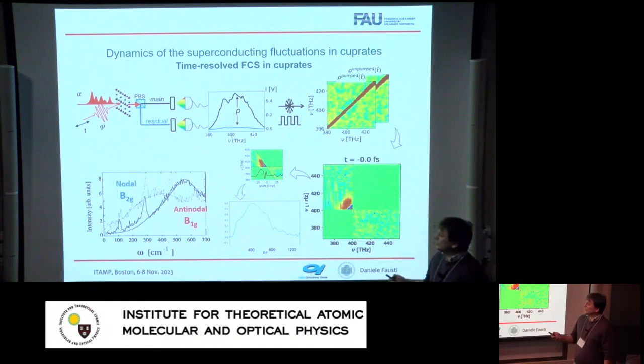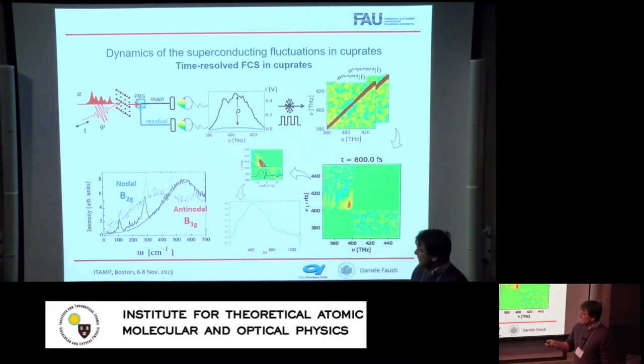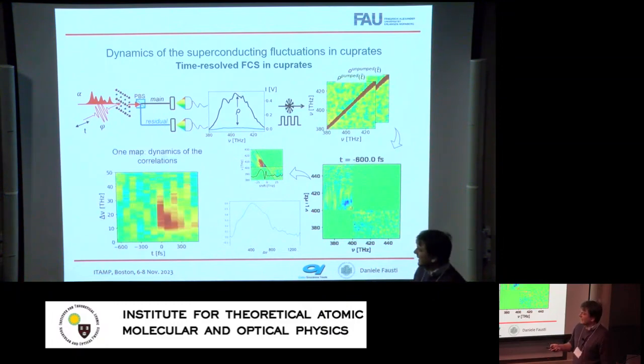What could turn out to be a very interesting observation is the following. Now I can measure how this Raman scattering evolves in time. So I can measure information which tells me, after I perturb the superconducting state, how the spectrum of electronic excitation evolves in time. And I see that I can measure the relaxation time of this scattering feature.